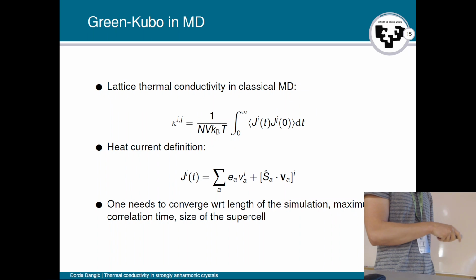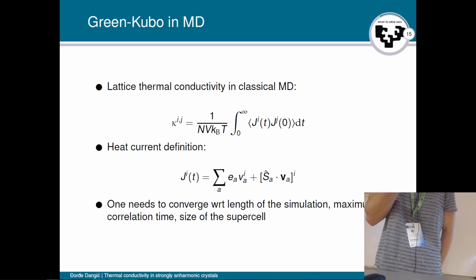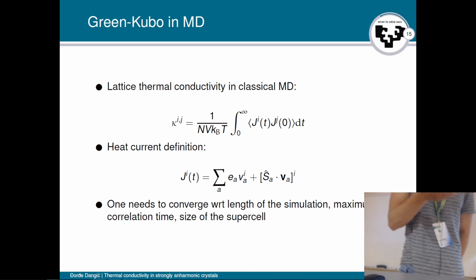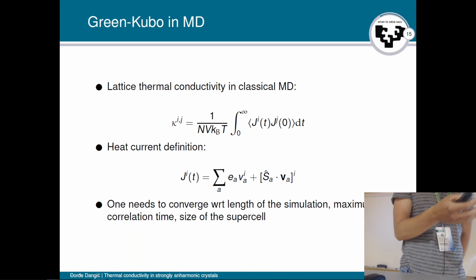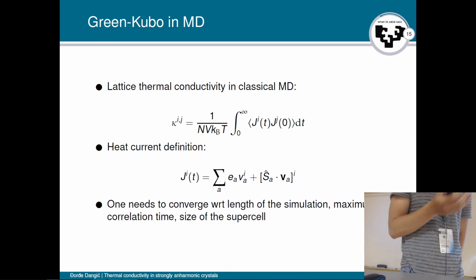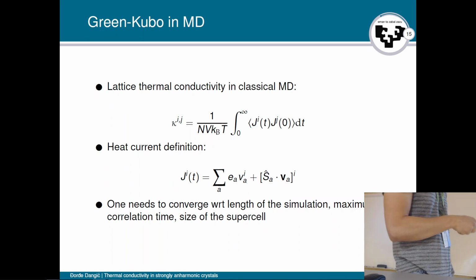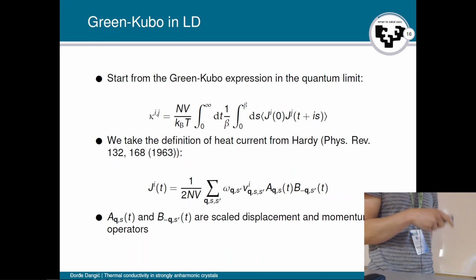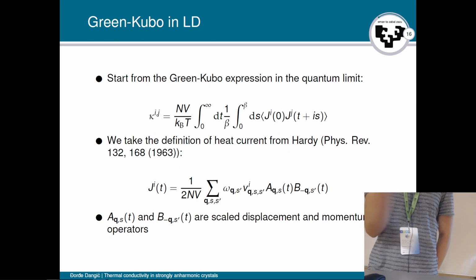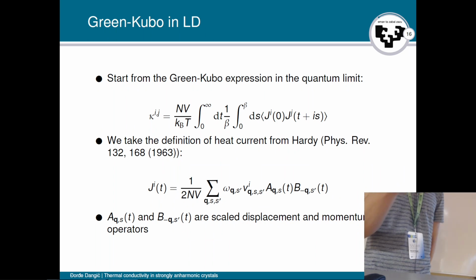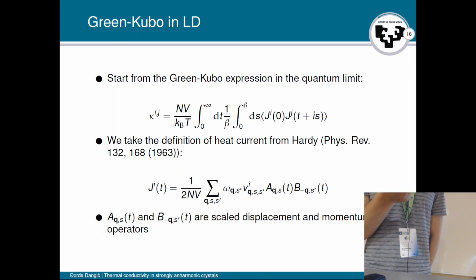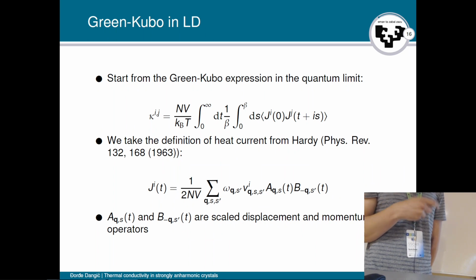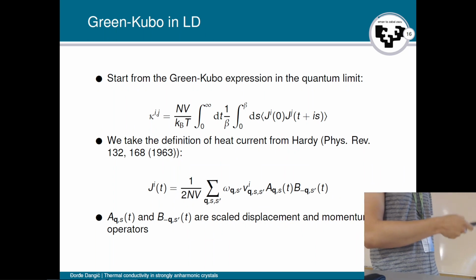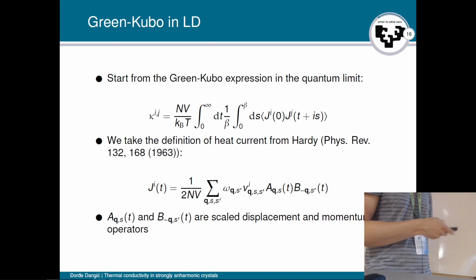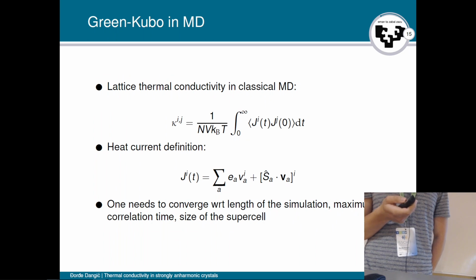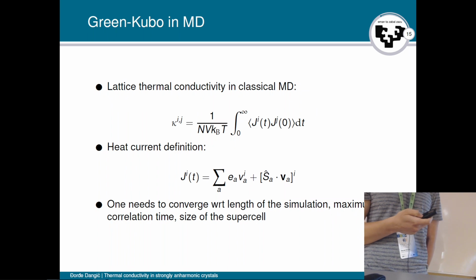The other one is that when you calculate the heat current in MD, you get a number for the lattice thermal conductivity, but you don't have any way of analyzing it. You don't know which phonon modes contribute the most, so you cannot know how to design your material to improve its performance. In this approach, where I have phonon modes, I can say I can stop this phonon mode if I make the crystal grain this size, or I can put this type of imperfection inside the crystal, and this will scatter the most heat-carrying modes. In MD, that's not possible. Obviously, MD has different advantages. In this approach I cannot break the translational symmetry of the crystal, while in MD I can put whatever I want and calculate the heat current. Those are the ones I can think of on the spot.